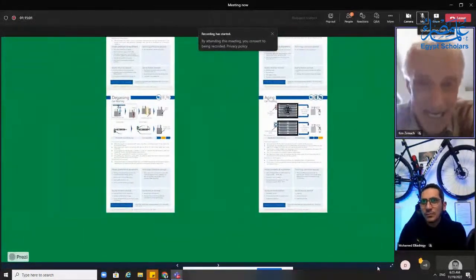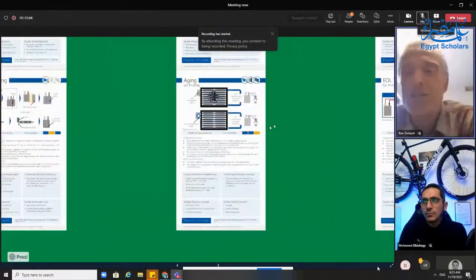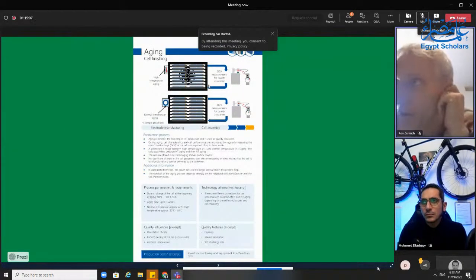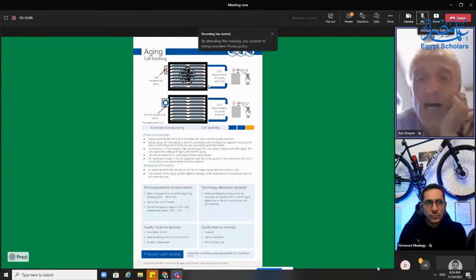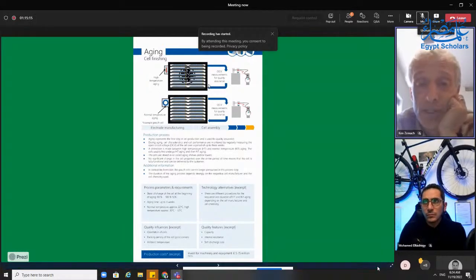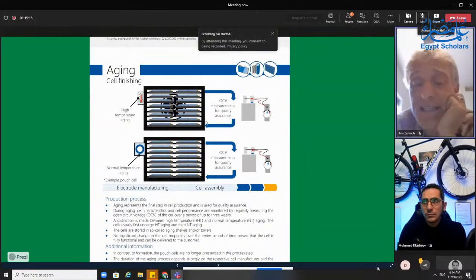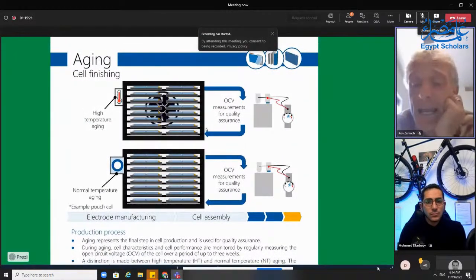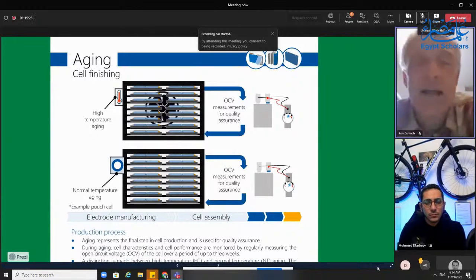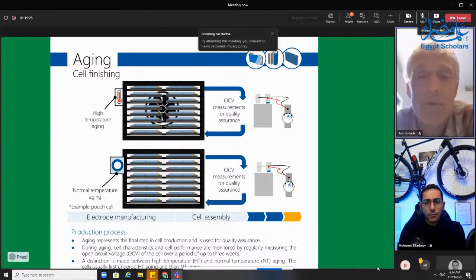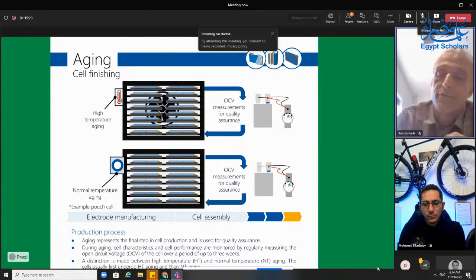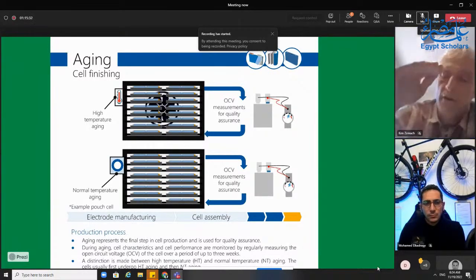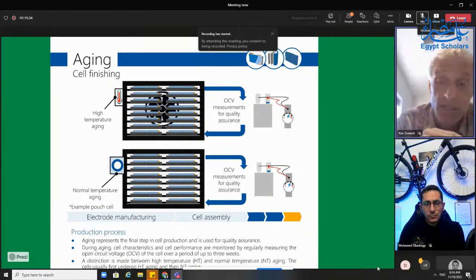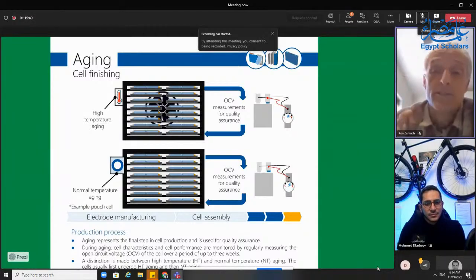Then you go into formation and aging. Formation and aging is where you're doing your initial charge and discharge cycles, because it's not really a battery until you've charged it up and discharged it and charged it up a couple of times. And let it sit to let more electrolyte soak in, and let it sit to let the SEI layer, the solid electrolyte interphase layer, form. And it's basically a series of very slow charges and very slow discharges. And then sometimes you let it sit for 24, 48, 60 hours at high temperature, depends.